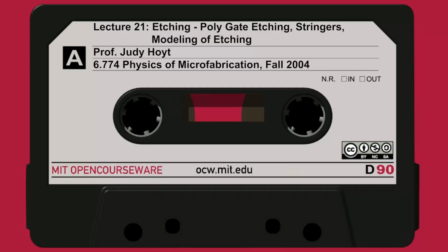Okay. Now, what you do is the polysilicon is then wet chemically etched and removed. So you etch with an etchant that digs out the poly. And if you want, you can even dig out the gate oxide and replace it with a high K. So this is what's called a replacement gate process. So you use poly, you etch your poly, you put down sidewall spacers, you go through the high temperature anneal.